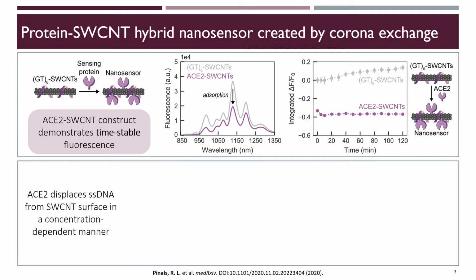We can then delve in a bit more to try to understand these molecular interactions in forming the nanosensors. I use a corona exchange assay previously developed to monitor the DNA displacement from the carbon nanotube surface by tracking the fluorophore tag on the DNA. Here, fluorophores in close proximity to the carbon nanotube surface are quenched and enter a bright state when desorbed into bulk solution.